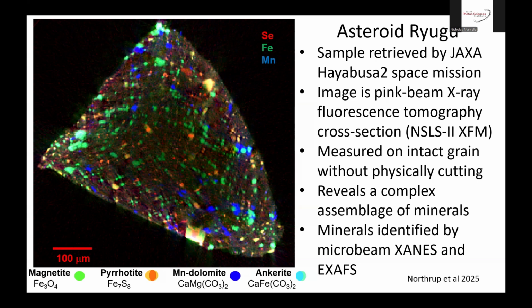This image is a pink beam X-ray fluorescence tomography cross-section run at the NSLS-II XFM beamline. So it's a virtual cross-section through a grain without physically slicing it. And it reveals a complex assemblage of minerals. Across the bottom there, there's a key of what minerals are different colors. This is a selenium, iron, and manganese map of the sample. And those specific minerals were identified by microbeam XANES and XAFS to confirm what they are. But you can see it's really a heterogeneous mixture of somewhat unusual phases.